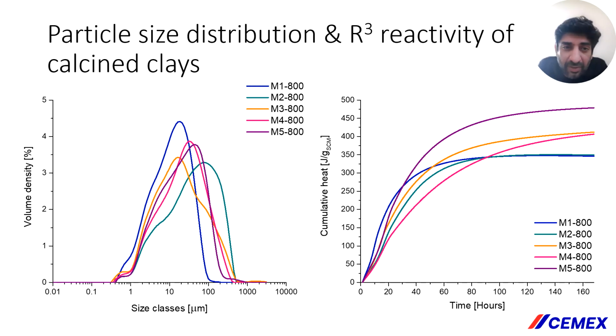The R3 test over a 7-day period showed M5800 to be significantly more reactive in comparison to all of the clays studied, despite having the lowest kaolinite content. But generally, the three clays of the Lias group, M3800, M4800, and M5800, were found to be significantly more reactive than the clays of the Ancombe group reported in the study. However, all 5 clays reported here meet the 90% confidence threshold to be classified as moderately reactive calcined clays. It must be pointed out that no definitive trends were apparent based on kaolinite content and particle size distribution alone.